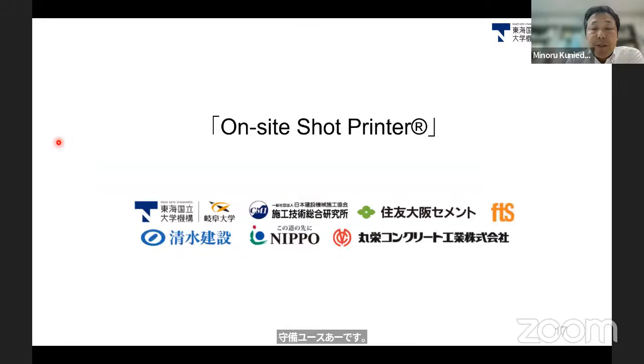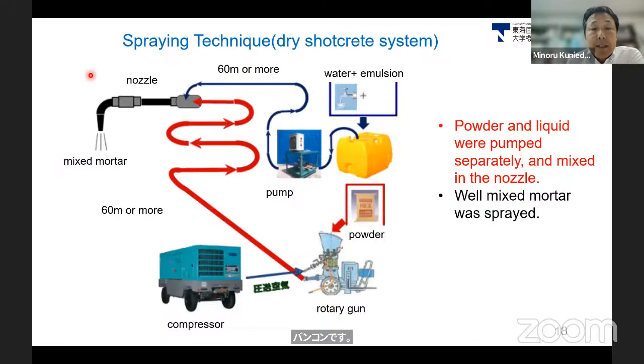So we try to develop an on-site shot printer covering those issues as I showed before. So the key technology is the spraying technique that has already been used in the tunneling method. The powder and the liquid, including emulsion, were pumped separately to the mixing nozzle. And then those materials are well mixed within the nozzle. And then the well mixed mortar is sprayed to the target. That is, no batching and mixing process is necessary.